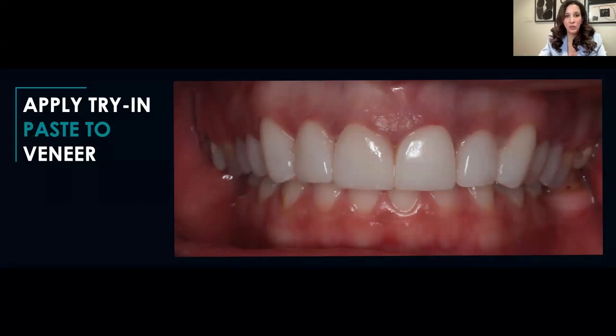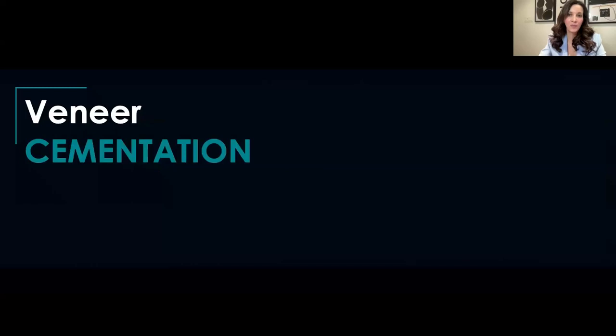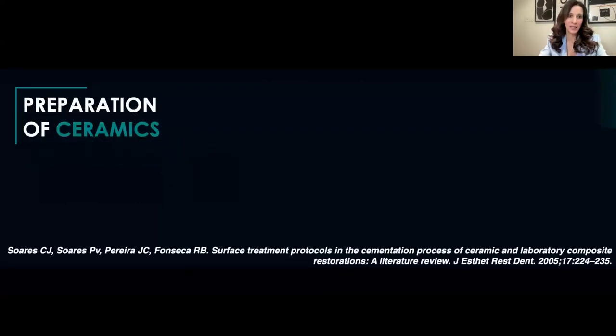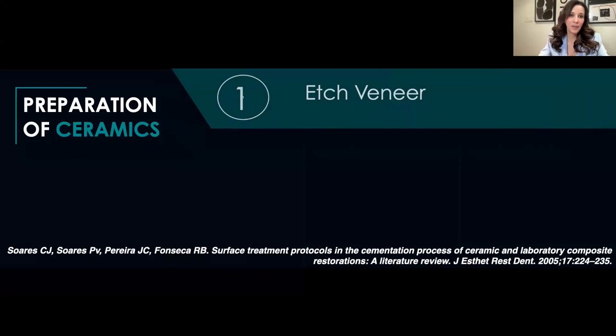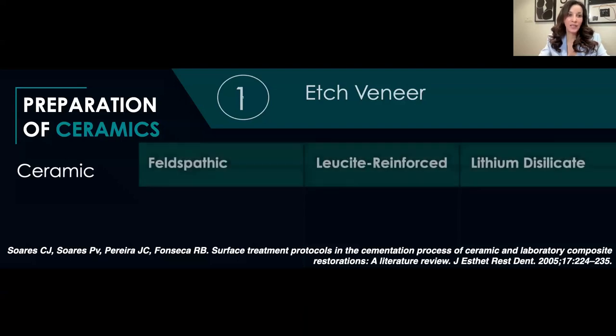So let's spend the next 2 to 3 minutes talking specifically about veneer cementation, because that tends to be very stressful for clinicians. I think it's one of the most time-consuming and technique-sensitive procedures we do as dentists. With regards to veneer cementation, the first step is that you have to etch the veneer. The duration of etching really depends on your material. Are you using a feldspathic, a leucite reinforced, or a lithium disilicate, so Empress or e.max glass ceramics?